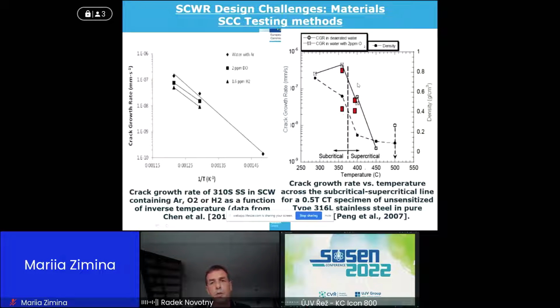On the right side is one of the oldest studies, where they exposed a 1/2 CT specimen, constantly loaded. In order to understand the whole thing, this crack growth rate test is performed in several steps. At the beginning, we are pre-fatiguing the crack using high amplitude, high frequency, and then we are slowly decreasing the load, and slowly decreasing frequency and amplitude up to switching to a constant load or constant stress situation.